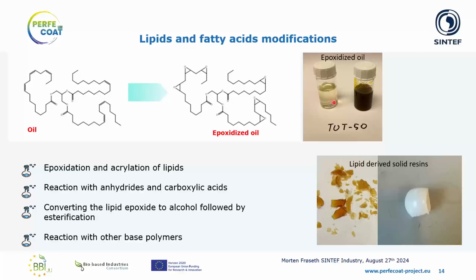The picture at the right here shows the change, which is quite important also, from the crude oil that we got to the epoxidized oil. So we see that the epoxidized oil has changed color much, from dark reddish to quite clear, which is an important change. We see here also some final solid resins that have been produced. We lack some control of the reactivity. This example here is by reacting the epoxide with anhydrides, but it has to be cured at 120 degrees. But we are trying to change that to be possible to cure at room temperature.